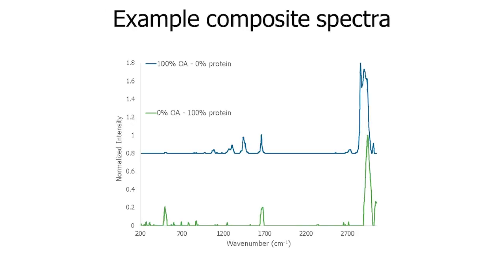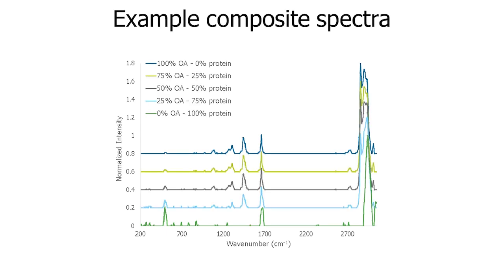Let's take a look at this reference database that we created. What you can see here are those pure oleic acid and pure protein spectra that were actually collected from real samples. These spectra were then combined in various ratios to calculate the composites that you see here. And this was to fill in the gap in that reference database.